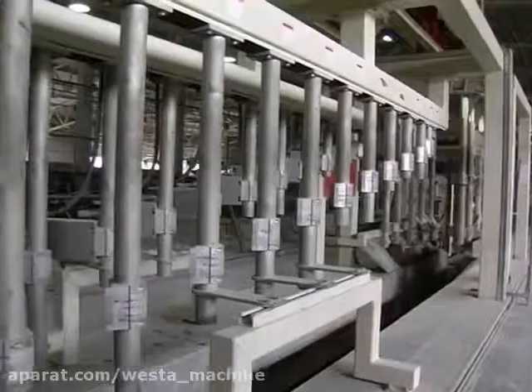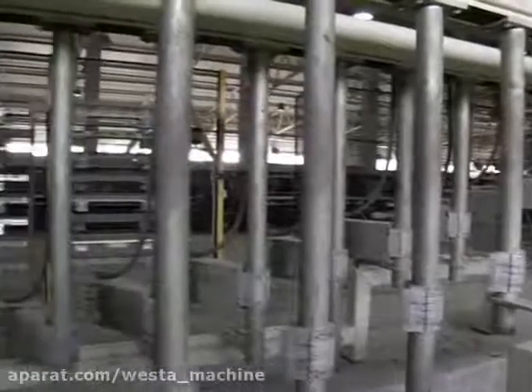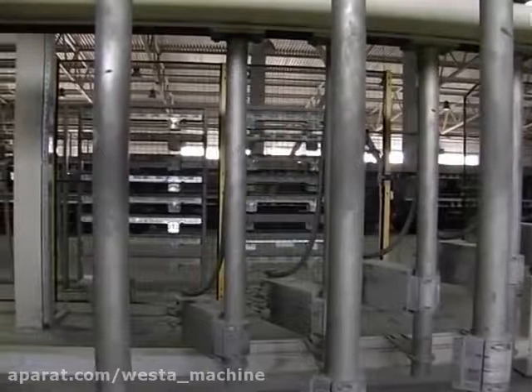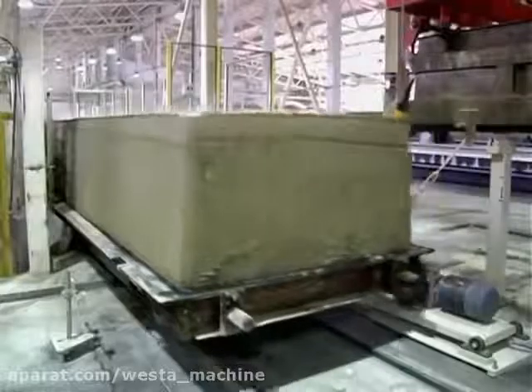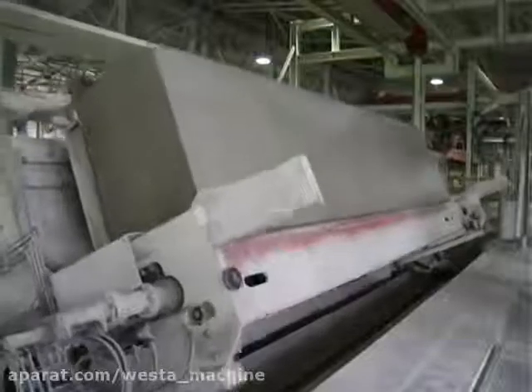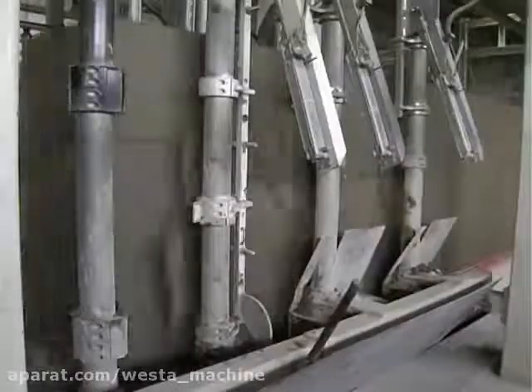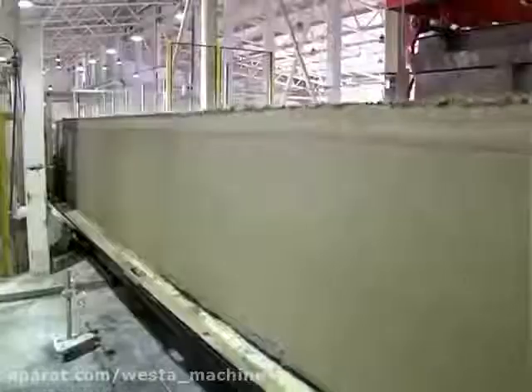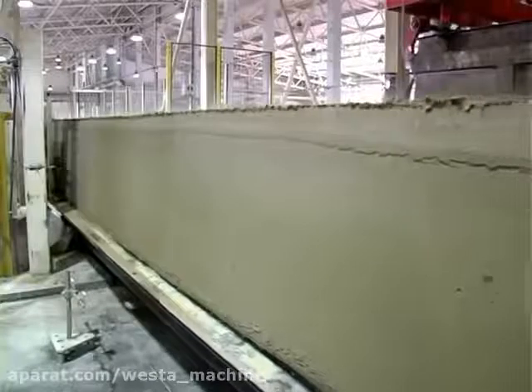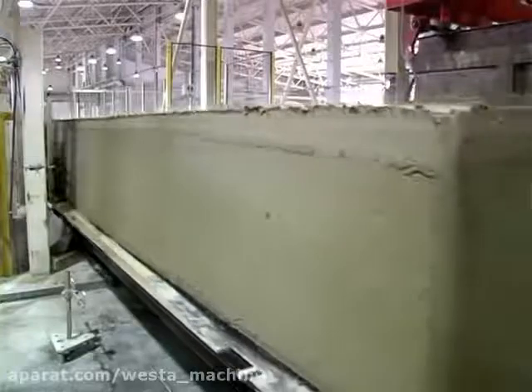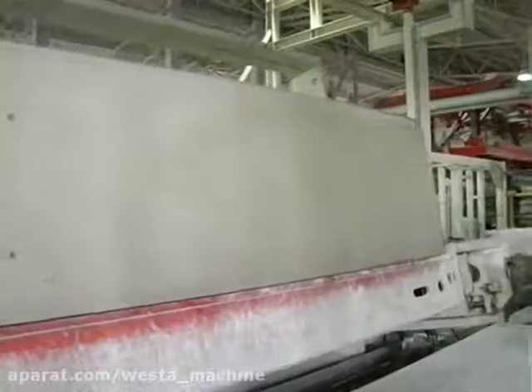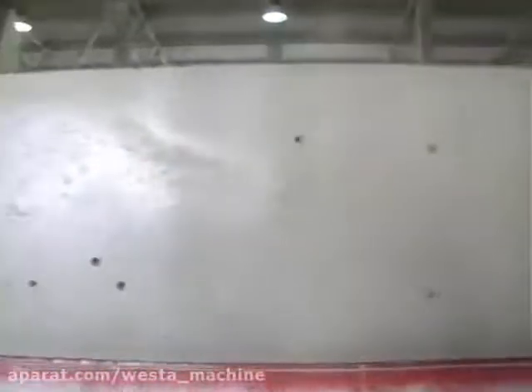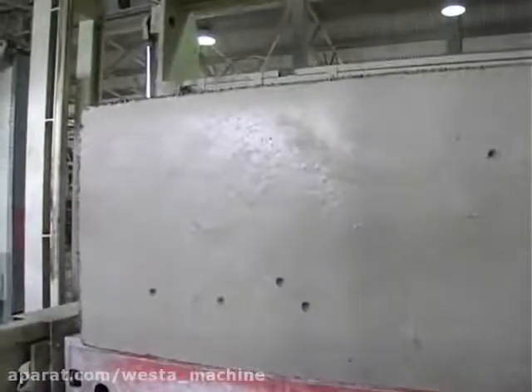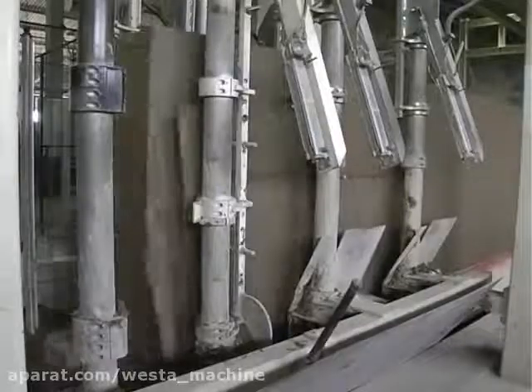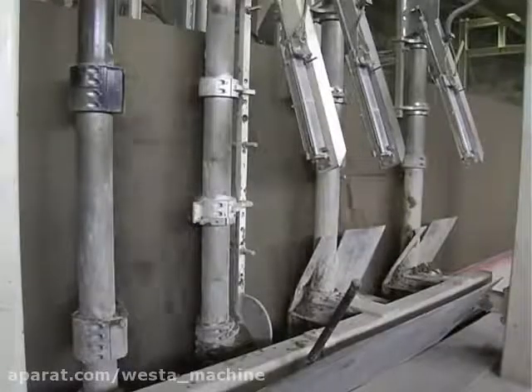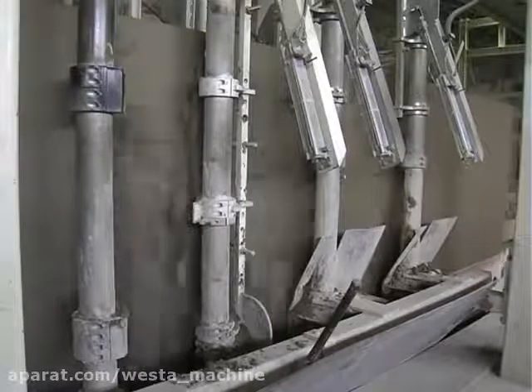The cutting line Wkb CL1 guarantees perfect quality of cutting and consists of the following key parts: pre-cutter, 2 tilting devices, vertical cutter, horizontal cutter and cross cutter. On the section of pre-cutting, a slope of the horizontally placed cake is cut at right angle. Then the cake is tilted at 90 degrees by the first tilting device on the cutting board, so the cake is standing upright. In the vertical cutter, the sides of the cake are cut, the length of the block is worked out and tongues, grooves, are inserted.